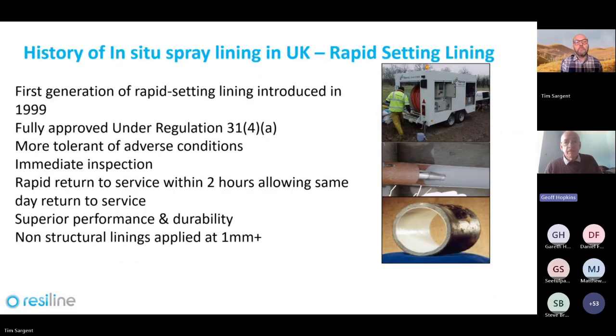Next slide, please, Tim. So there was quite a push during the 1990s to look at trying to find faster setting or rapid setting materials, and the first of these were introduced, obtained Reg 31 4A approval in 1999. The products had a number of advantages. They were more tolerant of adverse conditions. The coatings, because they set rapidly, weren't subject to so much water damage as was the case with epoxy coatings. And the initial coatings had a 2-hour return to service time, which gave you same-day return to service.